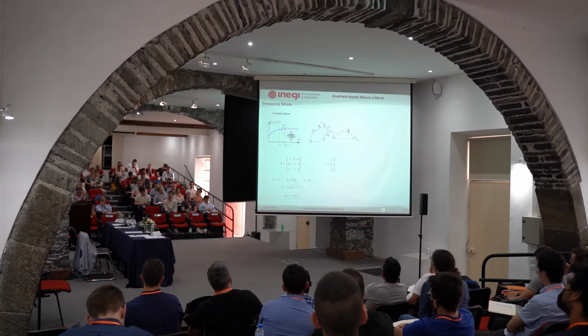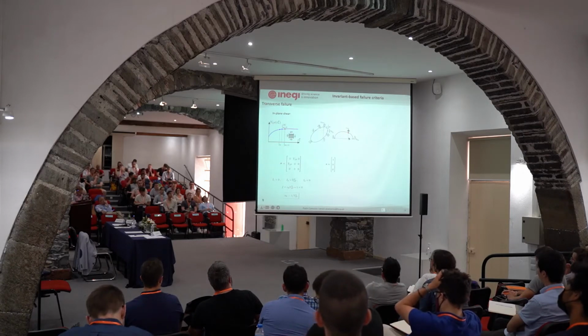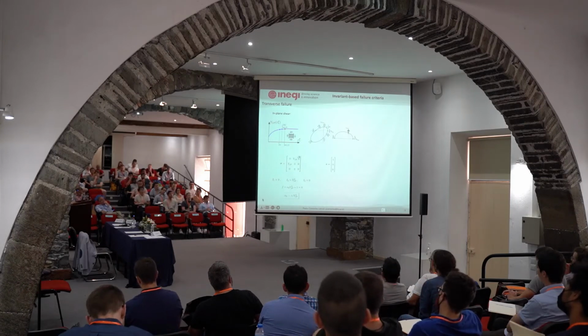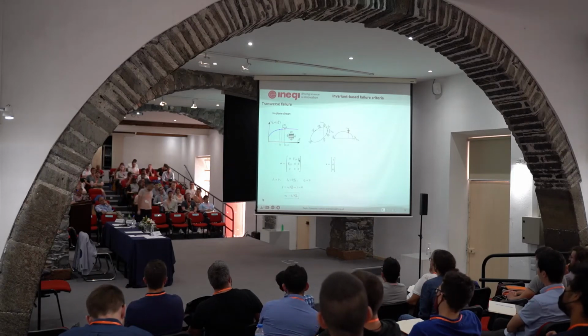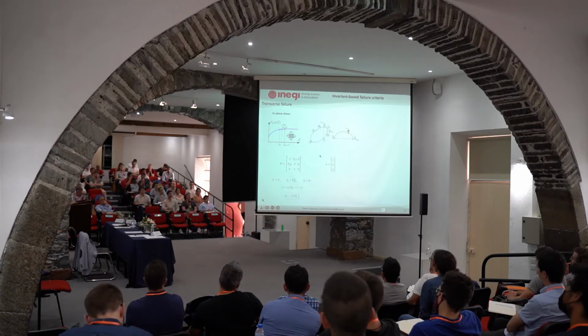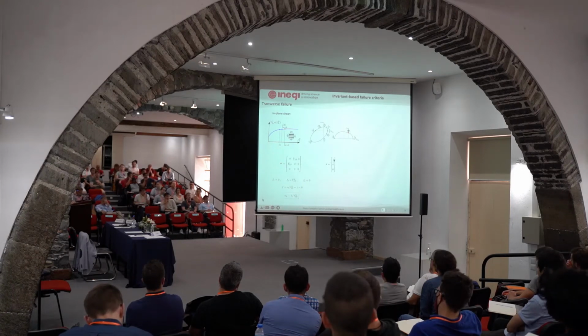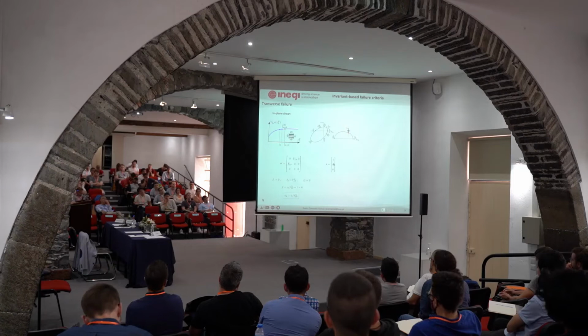So let's imagine that you apply in-plane shear. So we are loading your composite material along this line, okay, and to failure, okay? So I can project the relevant tensors in whatever frame I wish. I'm using the material frame for convenience, but of course this is based on invariance. I can use whatever I wish. So if I use the material frame, this is the stress tensor, and this is the unit vector that I use to form the structural tensor. If I now replace sigma and A in the invariants, you can see that the only non-zero one is I2. Okay? And my failure criterion results in this simplified expression.